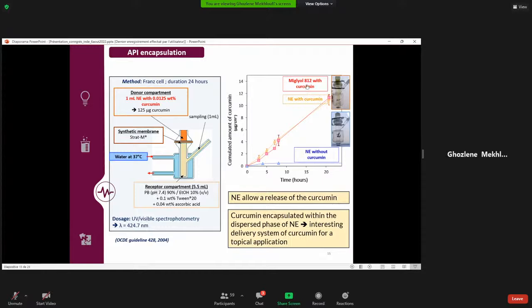In conclusion, we can say that we were able to increase the solubility of curcumin by solubilizing it into the oily phase of an oil in water nano-emulsion. Our study shows that the encapsulated curcumin did not disturb the droplet size and the stability of the nano-emulsion. We can also say that this drug delivery system allows the in vitro diffusion of the curcumin through a synthetic membrane. So the encapsulation of curcumin in nanoemulsion is an interesting delivery system of curcumin for a topical application. And it will be interesting to study this system deeper, for example, the antimicrobial effects or the skin penetration.